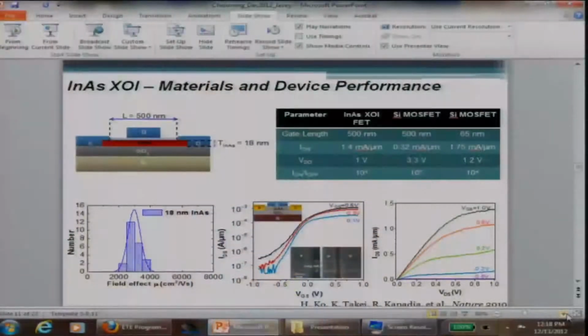So let me show you the transistor characteristics that we can obtain from this ultra-thin body indium arsenide XOI device. In this case, the gate length is about 500 nanometer. And look at this. The current drive for this relatively large channel length is pretty impressive already. Much higher than a silicon MOSFET with a comparable gate length, and getting close to, in this case, we had 65 nanometer data, 65 nanometer silicon MOSFET. So you can get pretty good current drives even at high gate lengths, and that's expected because the mobility is large.